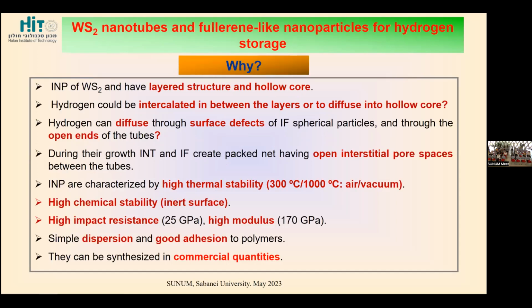So why did we decide to try to use these materials for hydrogen storage? There are a number of criteria that fit this task. For example, they have layered structure and hollow cores, or a lot of space to contain these materials. So hydrogen could be, in principle, intercalated in between the layers or diffused into the hollow core. Or there are a lot of surface defects which also can guide the molecules, hydrogen molecules or atoms inside. And there are interstitial porous spaces between the tubes.